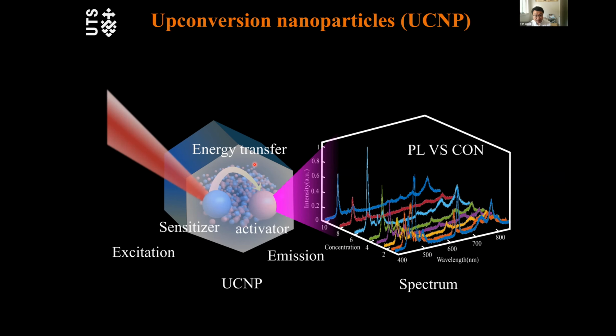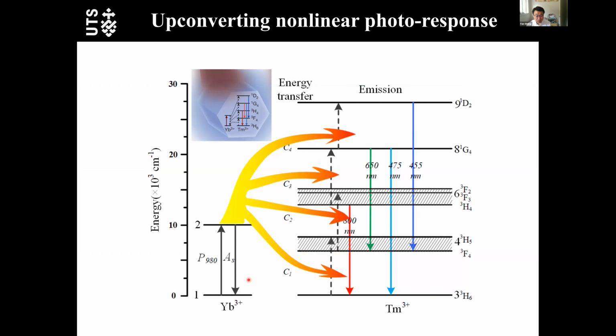What I mean is that inside this nanoparticle, they have a sensitizer to absorb a near infrared photon and an activator to give the emission. They have multicolor emission, and inside the nanoparticle there is an energy transfer process. Inside the particle, ytterbium absorbs a near infrared photon. Because the energy gap directly matches the near infrared, the absorption is linear, so the absorption is really, really strong. After absorbing the photon, the carrier passes the energy to another site, which is the emitter. This passing process is nonlinear.